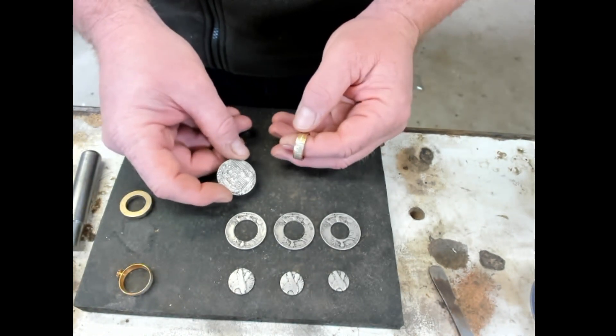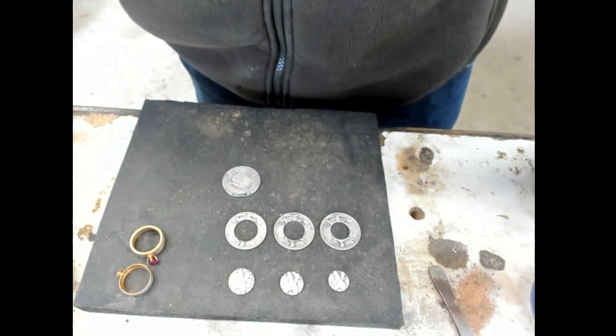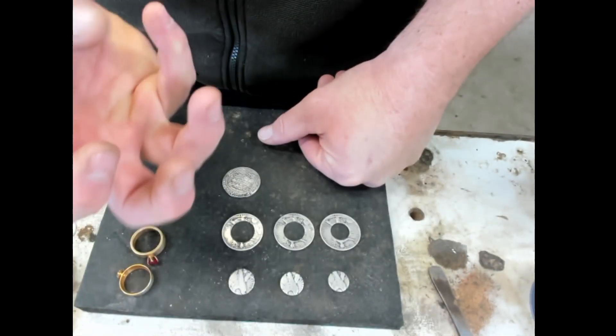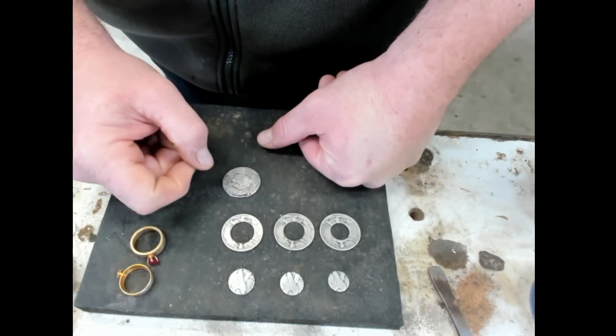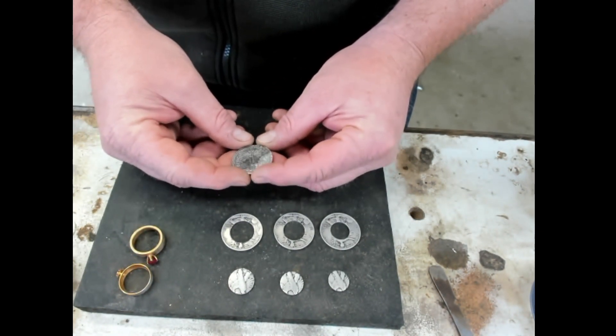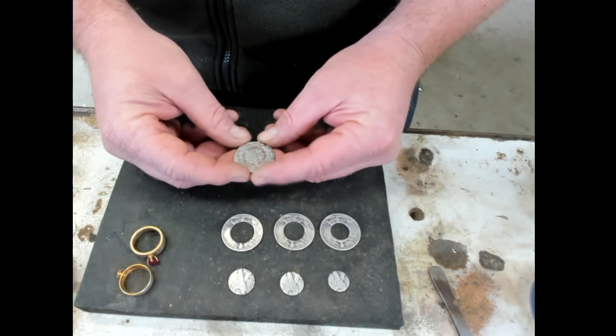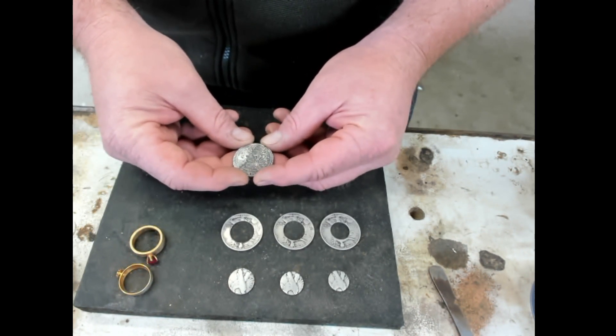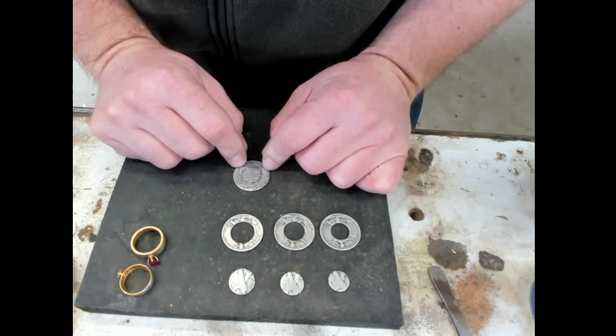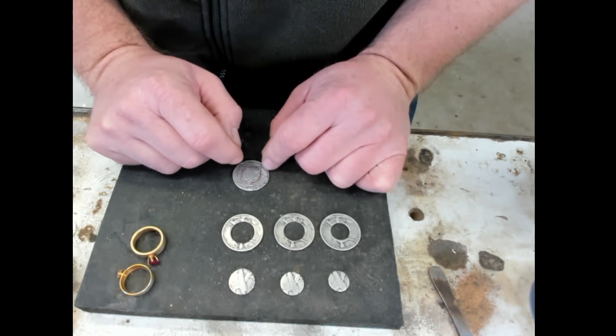First step is to anneal. I usually don't anneal on the rings I make anymore because I want to save the detail and leave the material work-hardened so you don't damage the detail. But I'm concerned about the work hardness on this coin because I'm seeing signs of surface weakness due to work hardness, so I'm going to anneal it first, then punch the hole. I'll probably put a piece of paper on the bottom and top to help protect the detail.